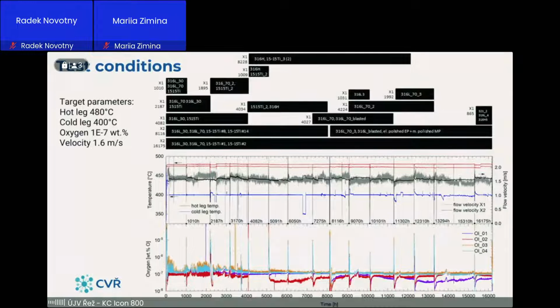Most important is the record of the oxygen sensors. There are 4 of them, and you can see that every 1,000 hours there was some peak of oxygen that was indicating our replacement of the specimens. In one leg, there were long-term specimens for 8,000 and 16,000 hours, and in another leg, there were short-term exposed specimens that were frequently replaced. So you can see it's a bit complex matrix.